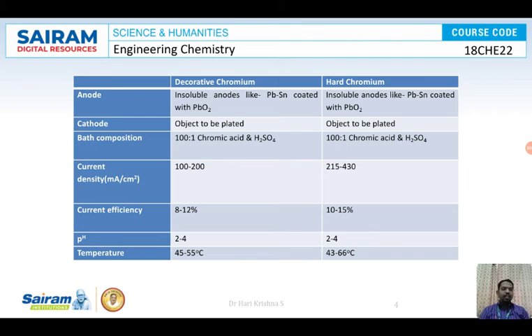So what are the other plating conditions? Let us see. The current density for decorative chromium plating is 100 to 200 milliamps per centimeter square. So what do you mean by current density? Current density is nothing but current per unit surface area of the object to be plated. What is the object to be plated here? It is the cathode. So current per unit surface area is called current density. For decorative chromium plating, it is 100 to 200. For hard chromium plating, it is 215 to 430. The current efficiency for decorative chromium plating is 8 to 12%. For hard chromium plating, it is 10 to 15%.